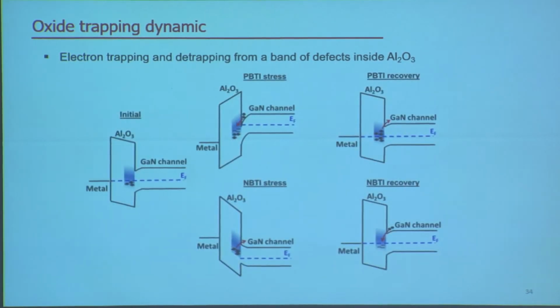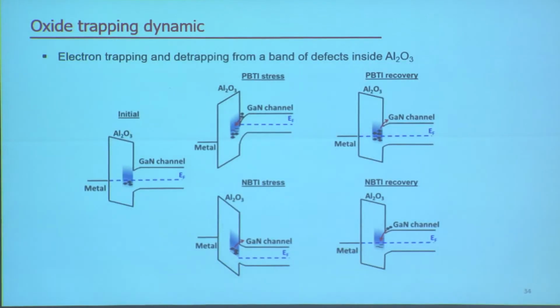So the dynamic of this oxide trapping is shown here with the energy band diagram. Initially, when devices are at rest, there are trapped states under the Fermi level inside the oxide. When we apply a positive gate bias stress, more states become available because they become below the Fermi level, and the gallium nitride channel can supply electrons to tunnel into these sites. That will introduce a positive threshold voltage shift. After the removal of the positive stress, the electrons can again be released back into the gallium nitride channel. And as you can see, there's a little bit of an energy barrier. That's why we saw earlier that there's a temperature dependence.